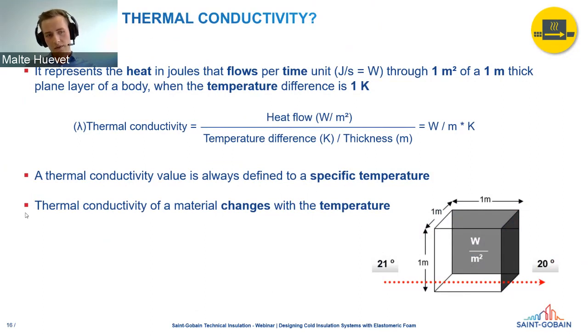If we also have a very big difference in temperatures, for example, if you get an insulation which should be used at, for example, minus 200 degrees, then you should also keep in mind that with the temperature, the thermal conductivity of the insulation material will change also. So, for example, at 0 degrees, we got maybe 0.33 watts per square meter Kelvin, and at minus 50 or minus 100 degrees, it can be already at 0.2, for example. That should be also taken into account, because that's the reason why there's always a formula given in the technical data sheet, and then we should calculate the thermal conductivity related to the point and to the temperature.